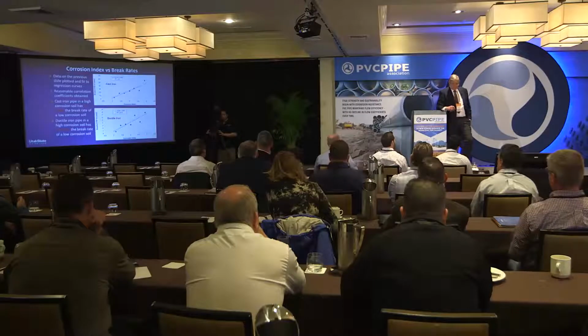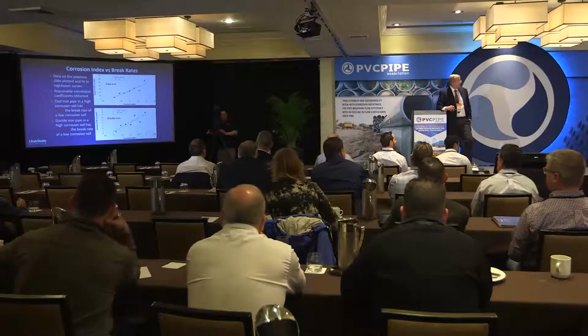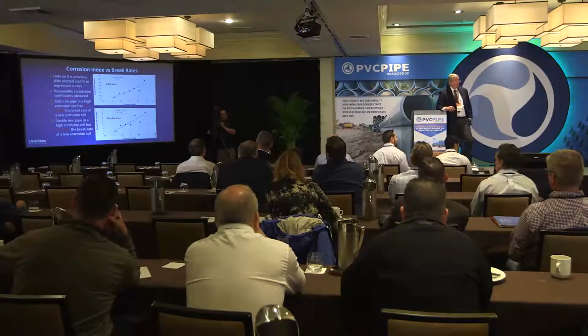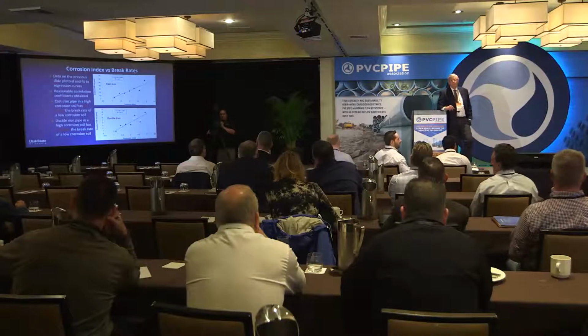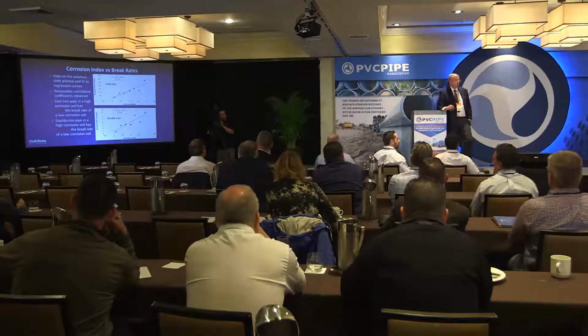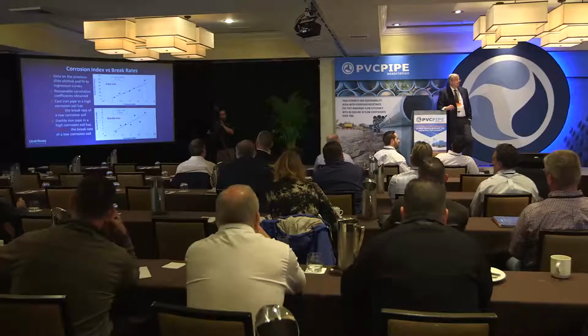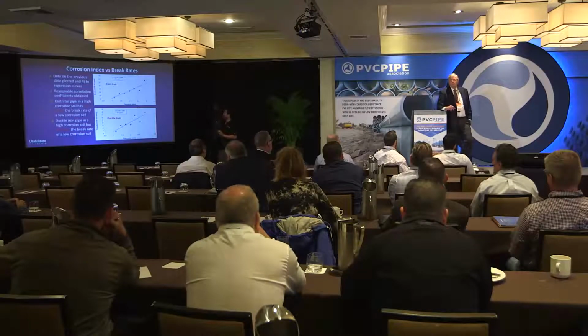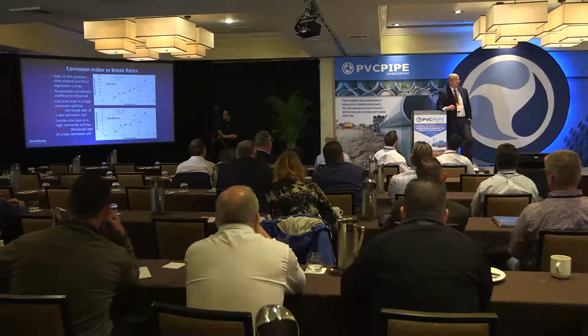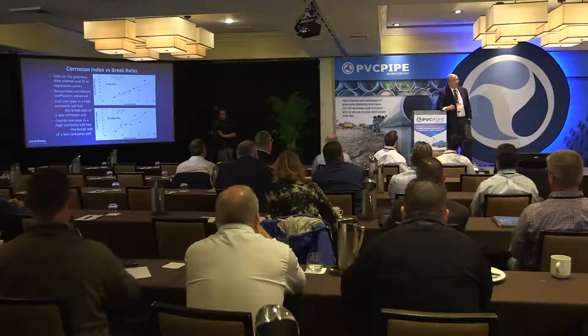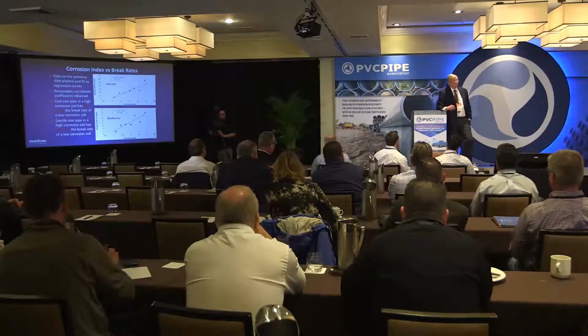If we look at ductile iron, we're seeing a factor of 10 between a low corrosion index soil and a high corrosion index soil. I forecast there'll be a lot of cities that read this report and take a look at their own corrosion index. Smart cities, like the Logan I come from, they like their ductile iron.